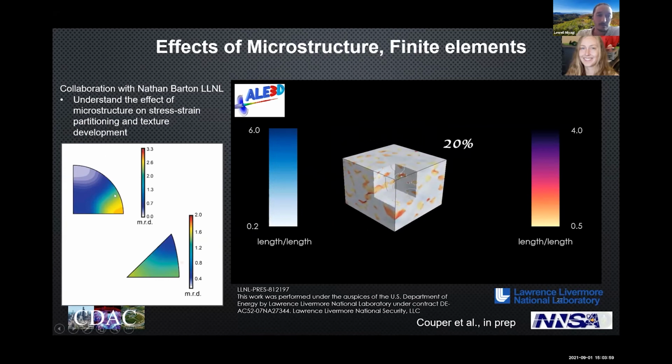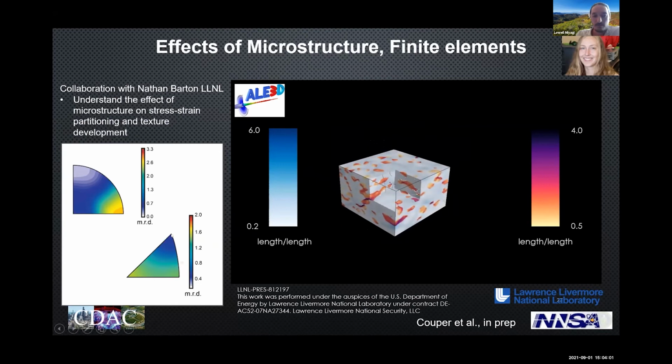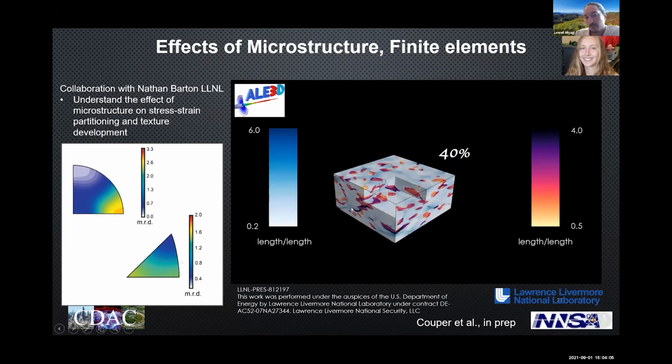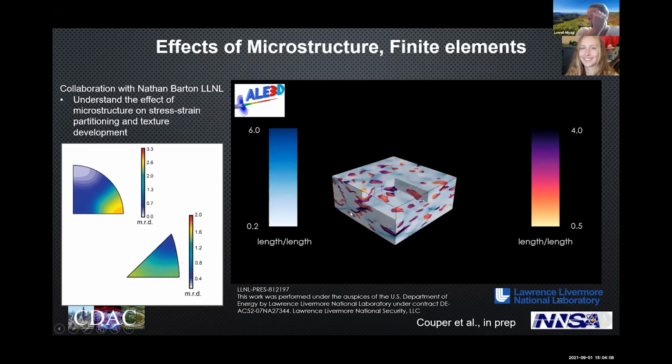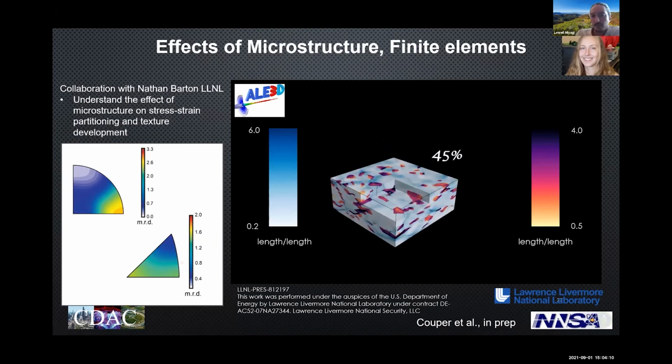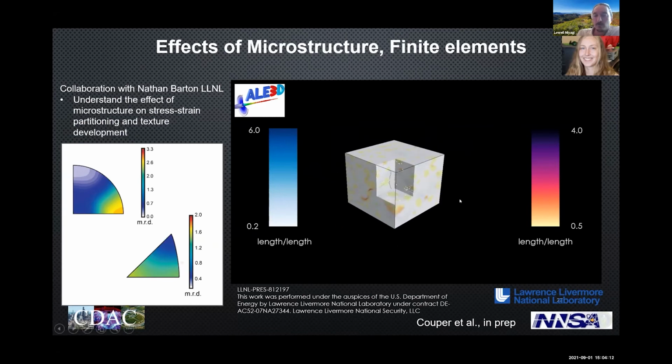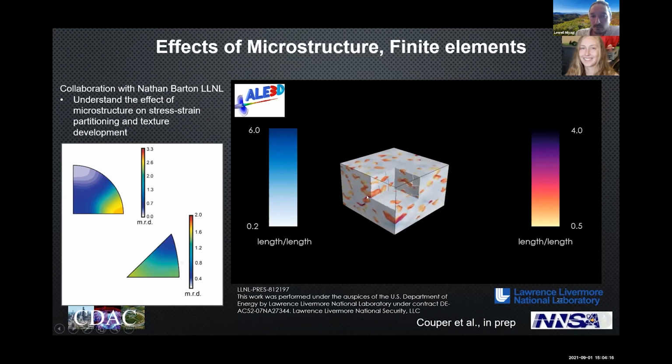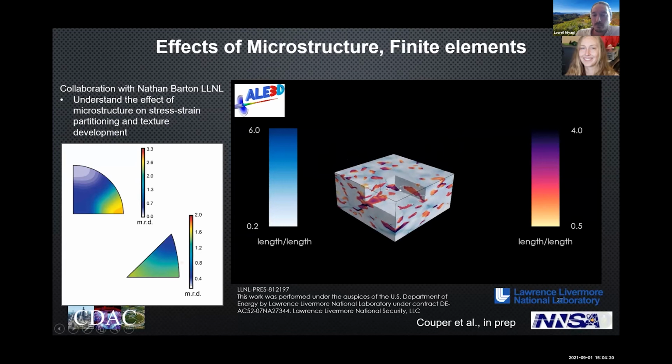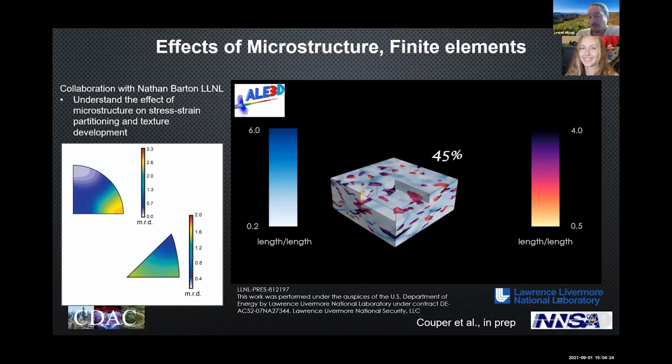So the bridgmanite texture is actually quite a bit stronger than first appears if you don't look at the scale bar. The other really interesting thing I think that you see here is if you notice, particularly in the MgO phase, as a simulation runs, you can see higher strain regions developing inside each grain. Okay, so the strain is very heterogeneous within the grains.